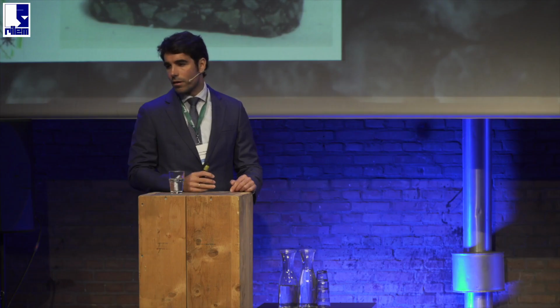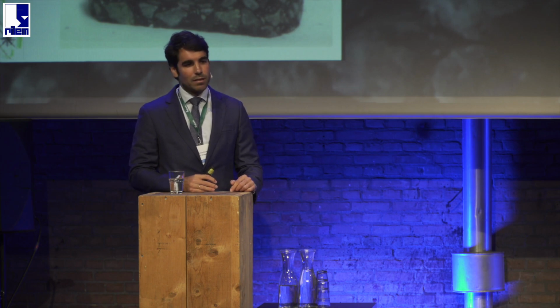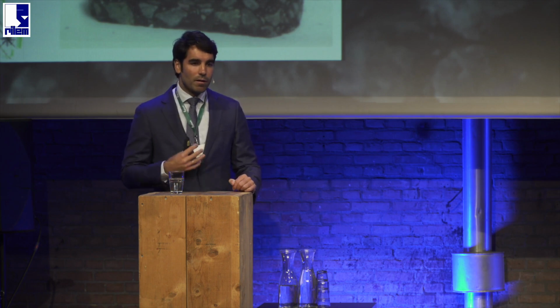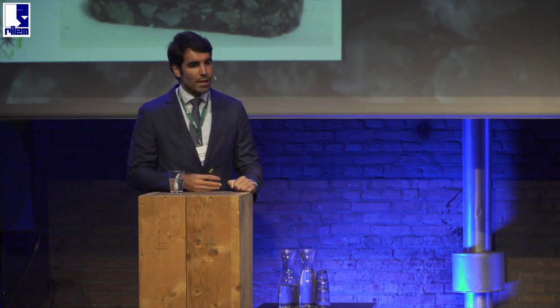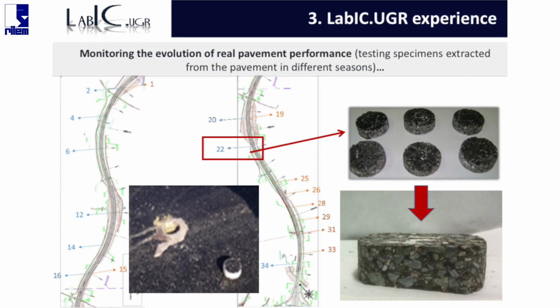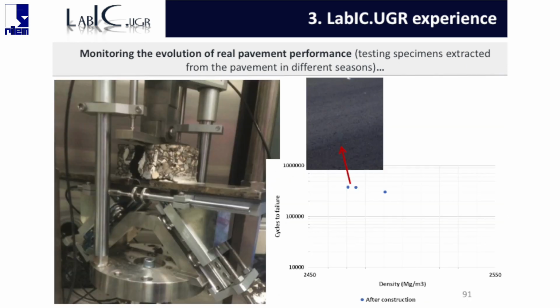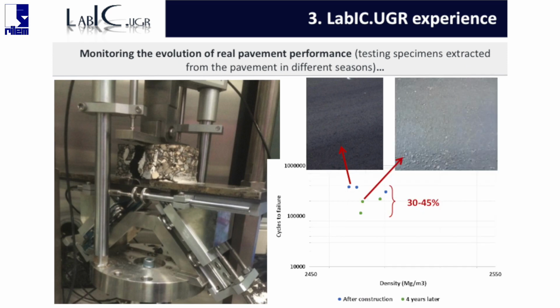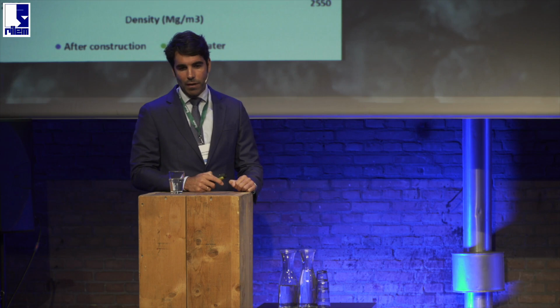And finally, another interesting application of this test is the monitoring of the performance of the asphalt layer constructed in a real road. For that purpose, we organize different campaigns of cores. We take different cores in different seasons from the road, and we evaluate them in the fatigue asphalt cracking test. We determine the fatigue life after the construction, and then after different periods, for example after 4 years, and we obtain the reduction of the fatigue life.